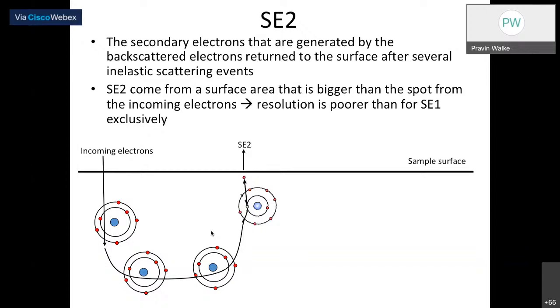Those secondary electrons are usually generated by the backscattered electrons. Those backscattered electrons return to the surface after several inelastic scatterings inside the specimen. There are several atoms deeper inside the specimen. If your incoming electron does not collide with the surface atoms, then it will go to the deeper atoms, and at the deeper atoms it may or may not have an interaction. If it interacts at one of the deeper atoms, it releases secondary electrons that reach the surface, and that is called a secondary electron (SE2), right?